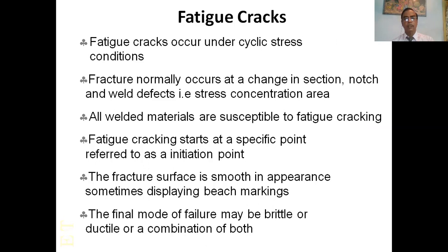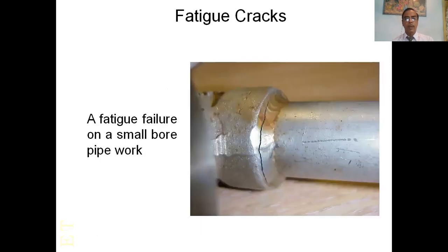Fatigue crack. Fatigue cracks occur under cyclic stress conditions. Fracture normally occurs at a change in section, notch, and weld defects, that is, stress concentration areas. All weld materials are susceptible to fatigue cracking. Fatigue cracking starts at a specific point, referred to as the initiation point. The fracture surface is smooth in appearance, sometimes displaying beach markings. The final mode of failure may be brittle or ductile or a combination of both. Fatigue failure on a small bore pipe work.